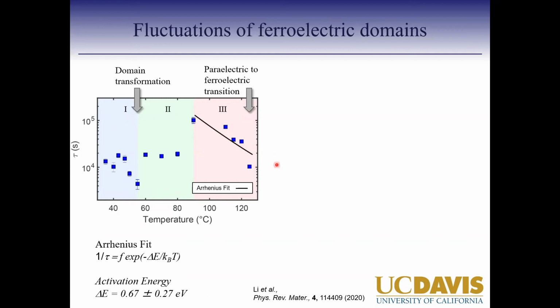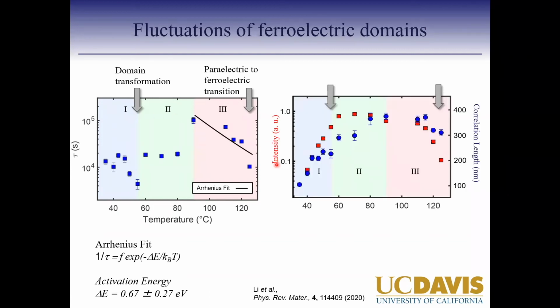And that sort of correlates with the intensity and the correlation length of this material as well, where if I look at the intensity, which is the red data points, as AC domains are appearing, the intensity increases. In the second regime, where most of the things are stable, there are still small fluctuations, and the intensity of these domains stays. And then as I get to the Curie temperature, the intensity starts to disappear. However, interestingly, the correlation length doesn't exactly follow the intensity. In this case, it linearly increases. As you have more and more AC domains, you have higher correlation length.